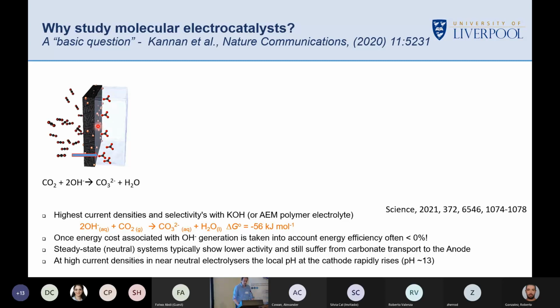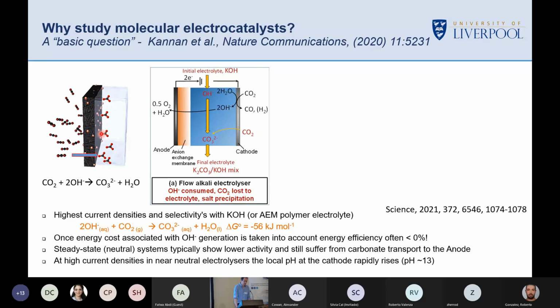So we're going to use these gas diffusion electrodes. We're going to pass high concentrations of CO2 through the back of a porous electrode where our catalyst is going to be sitting. And the reality is that a large amount of this CO2 is going to be lost into the electrolyte. And in fact, it gets slightly worse than that. If we start to think about what happens, we're not just going to lose the CO2 into the electrolyte, we're going to consume hydroxide. So we've got a gas diffusion electrode in contact with a liquid electrolyte, so a strong base. We're going to consume some of the hydroxide, and we're going to then need to replace this, at an energy cost, of course, in generating the hydroxide.